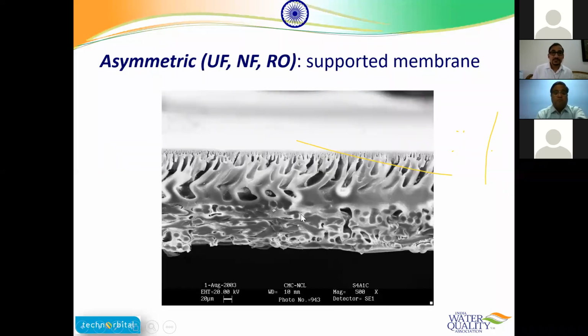Now these asymmetric membranes, mostly all the UF, ultrafiltration, nanofiltration, RO, even microfiltration, these are all asymmetric membranes. If you see, this is again a highly magnified cross section under a microscope. The top has very fine pores, maybe 5 to 10 nanometer size. Then below that, there are big size pores, maximum 100 nanometers. And then again at the bottom, you have very fine pores. So these are asymmetric membranes.